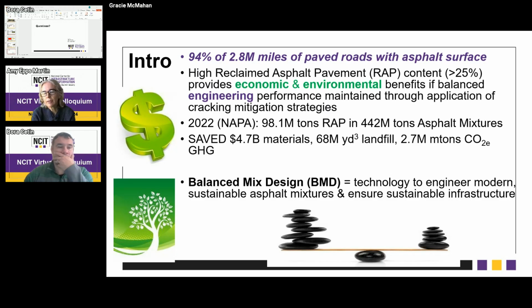So right now, the current standard or average, I guess, for all of the states is about 20% of our new hot mix asphalt mixtures, of those 440 million tons produced. About 20% of those are RAP across the country. And so we're trying to up that value. We're trying to increase our RAP contents above 25%. And we want to do that for 3 reasons. The 3 E's is what I say.